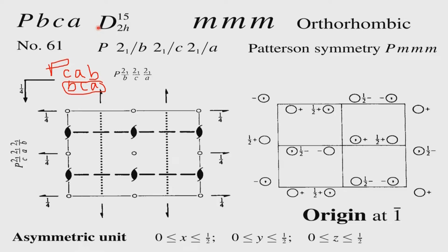Suppose that molecule has a very special behavior. Suppose there is one direction which is very, very large, and that is the direction which is very crucial for the property that compound is showing. And that happens to tell us that the space group is PCAB and that large direction is B. Then we would rather keep it in this form than report as PBCA. So, you will see a lot of literature, particularly in inorganic compounds and also in materials oriented compounds, where the space groups which are not the normal space groups are acceptable.